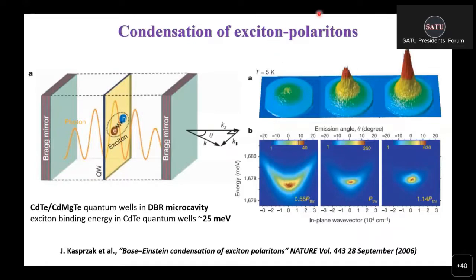Because exciton polaritons is a kind of boson particle, the boson particles can accumulate at the same quantum state within their carrier lifetime. However, because the exciton binding energy of this semiconductor is about 25 millielectron volts, the phenomena of condensation can only be observed at very low temperature.